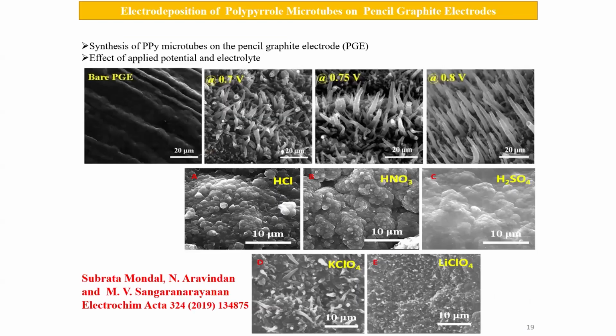Then here we prepared polypyrrole conducting polymer using again the same electrodeposition technique. This we used for supercapacitor purposes. No time for supercapacitors today, it's a big field, but you can see we have taken a pencil graphite electrode and synthesized polypyrrole microtubes. All these are microtubes, in various electrolytes: HCl, nitric acid, sulfuric acid. Again, a very simple electrodeposition technique, nothing exotic. Then we used it for studying as a supercapacitor material.